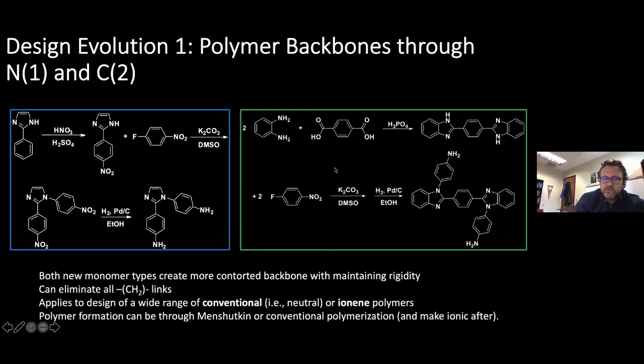The other interesting thing is to make imidazole structures from benzimidazoles that are effectively bent as well. We see here what's called a bi-imidazole structure, where the two imidazoles are linked between the 2 positions by an aromatic ring. So there are lots of new design possibilities. With polymers we've already made from this, I don't have all the data, but the thermal stability goes up even more, close to 500 C, when we take this approach and make everything even more aromatic.